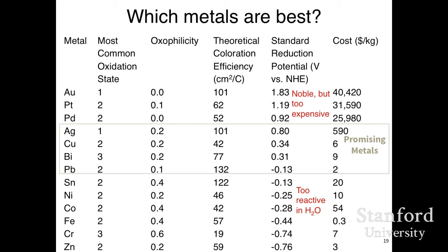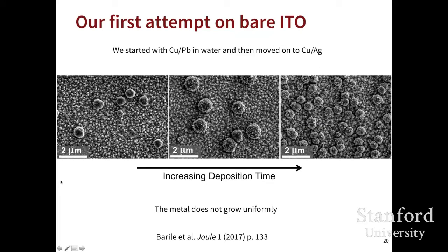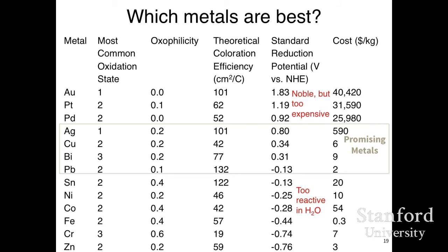The postdoc in my group, Chris Barile, thought carefully about what metals should be used, and he created this table. And down at the bottom of the table are some candidate materials that would be inexpensive, but these materials are hard to plate, and it would be very difficult to reversibly plate them, because they're very prone to oxidation, and once they oxidize, then it's hard to strip them. If we go up to the top, things like gold, platinum, palladium, they're very resistant to oxidizing. However, perhaps for the same reason, they're very expensive metals. So in between are some attractive candidates: silver, copper, bismuth, lead. And we found that they work very well.